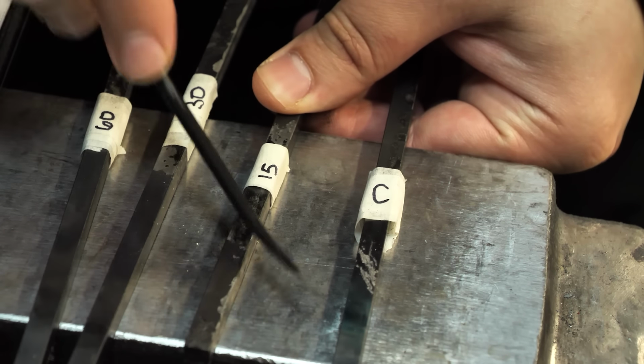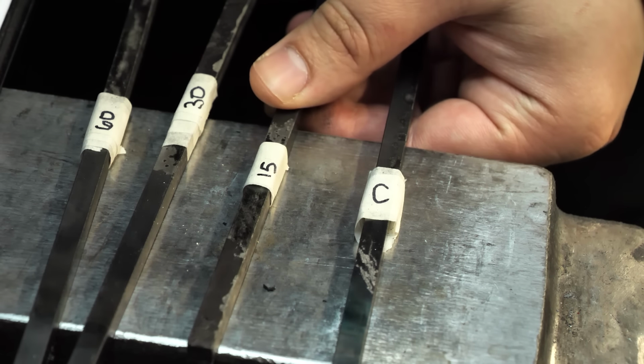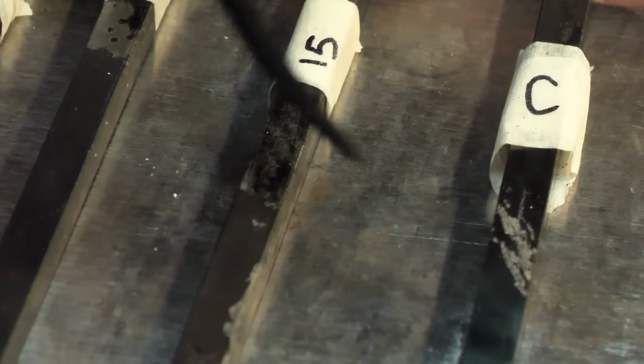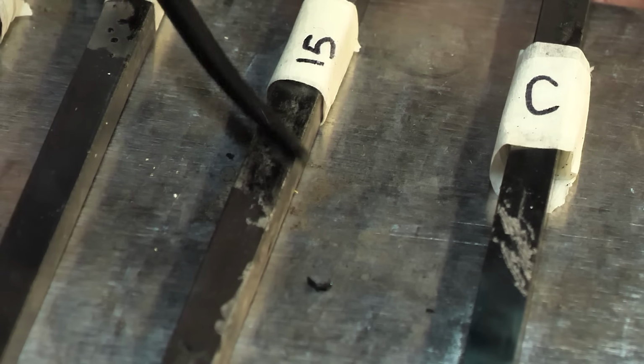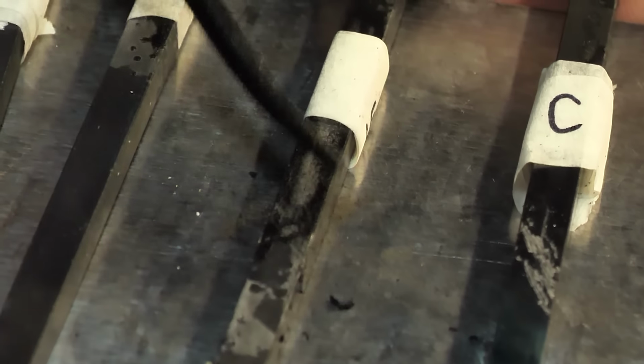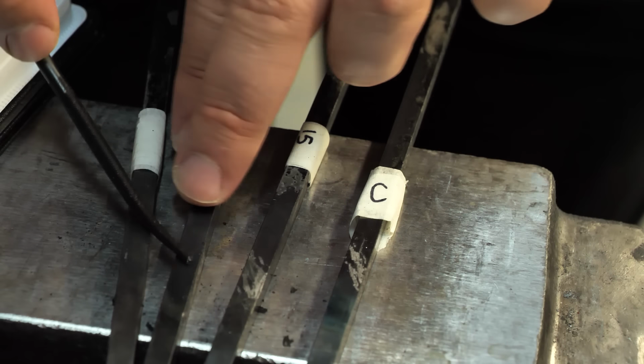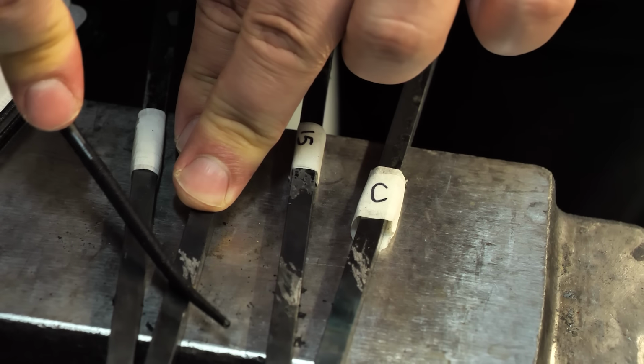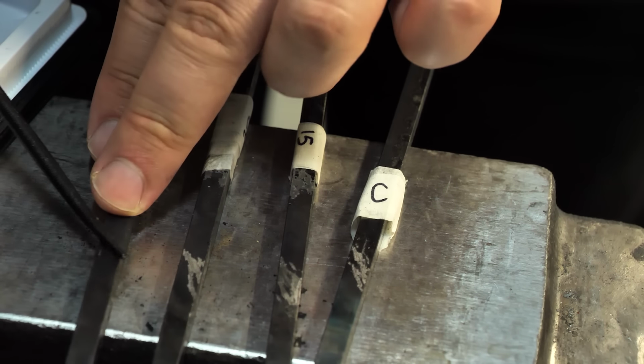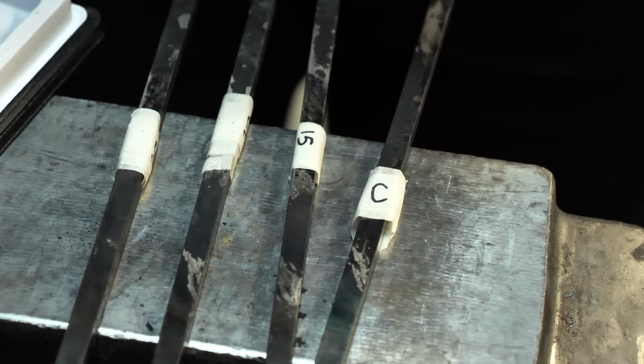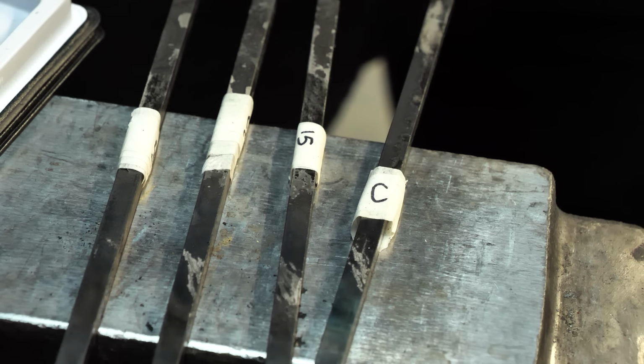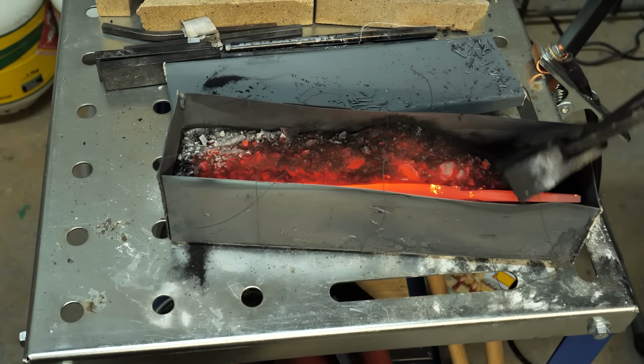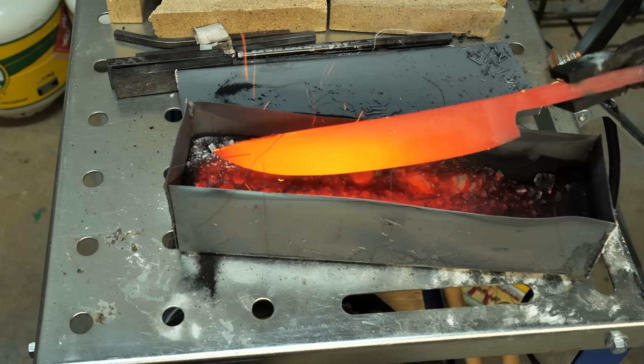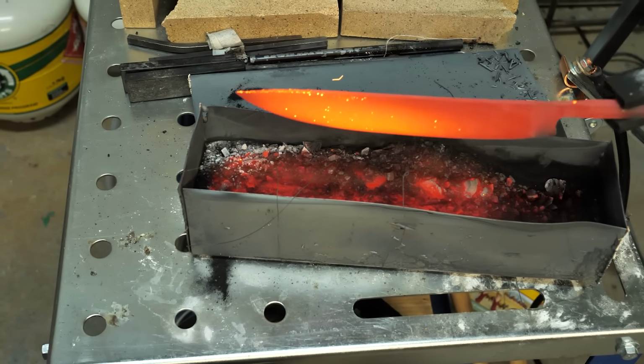But the case-hardened pieces are very different. Even after 15 minutes, there's now a very hard skin on the outside, and it takes a 55 Rockwell file to cut it. As we go up in time, this only gets better, and by the 60-minute sample, only the highest 65 Rockwell file got any purchase, and even then only barely. So, as you can see, this is a really fast and effective way to turn crap iron into a usable tool.